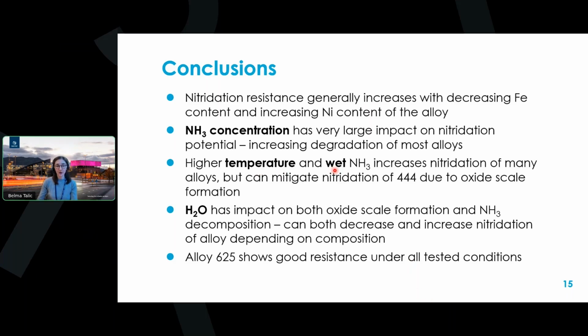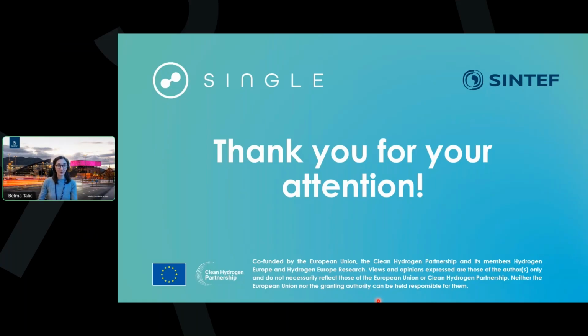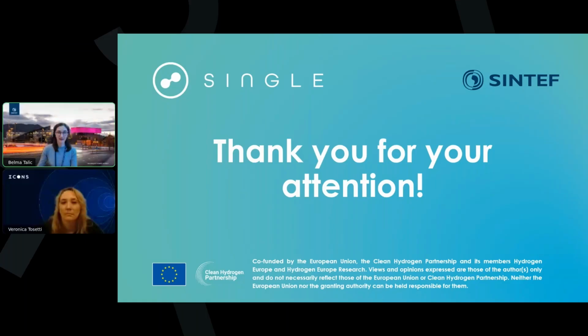We also saw that increasing temperature and wet ammonia increased nitridation of many alloys, but for some, such as the ferritic stainless steel 444, it can actually mitigate nitridation because it promotes formation of an oxide scale. Steam had an impact on both oxide scale formation and the ammonia decomposition. So depending on the type of alloy, it can both decrease and increase nitridation of the alloy. And finally, we concluded that alloy 625 was the alloy that we tested that had the best resistance when we considered all of the different testing conditions. So with that, I would like to thank you all for the attention and welcome any questions.